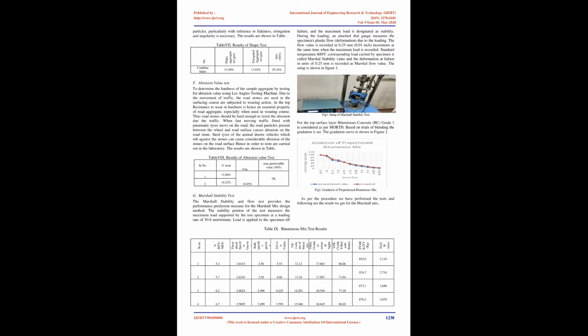Yanping Yin et al., 2017, showed a study on the effect of chemical composition of aggregate on interfacial adhesion property between aggregate and asphalt. This study compared the interfacial adhesion properties of asphalt with limestone aggregate and asphalt with granite aggregate. The main chemical compositions of limestone and granite are CaCO3 and SiO2, respectively. The results show that the interfacial adhesion strength of the asphalt with limestone aggregate is higher than that of the asphalt with granite aggregate.